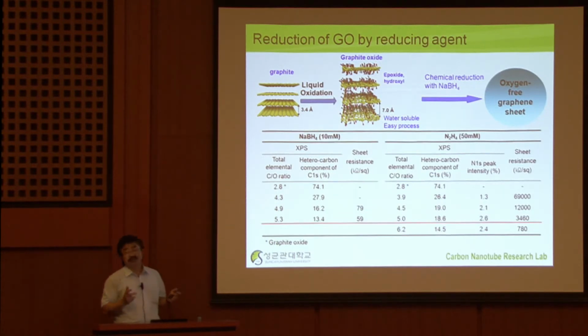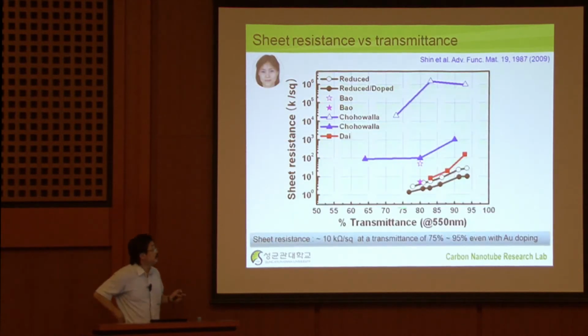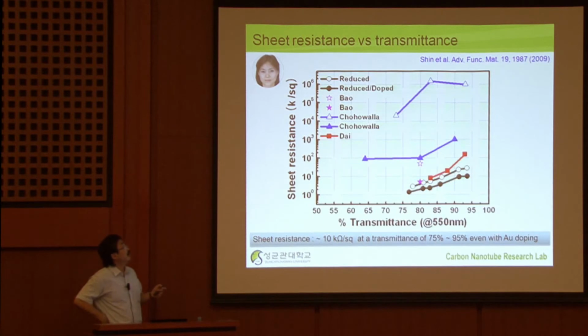Of course, during this process, we can have a reduction process to remove some of the oxygen groups, because oxygen functional groups basically increase the resistance of the graphite oxide. So to some degree, we have to remove them while we are keeping the solubility of the powder in water solution. And then we can simply measure this sheet resistance again. Whatever we do, the technology we developed in our carbon nanotube research, we apply the same thing here. Of course, we see this improvement. But if you look at the absolute value, still this is far from the real application. So with this approach, the graphite powder, there's no way for us to obtain high quality conducting film using the graphite oxide approach.